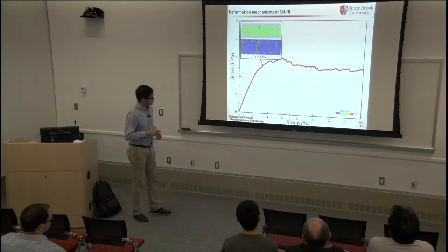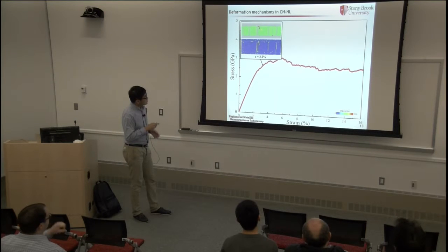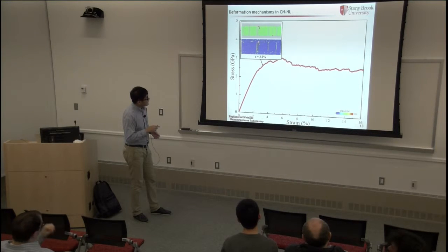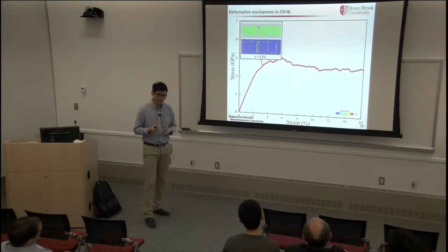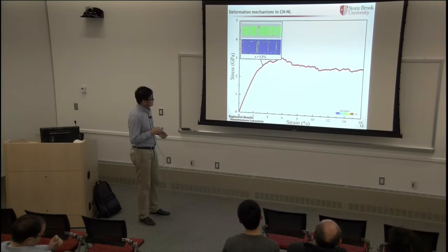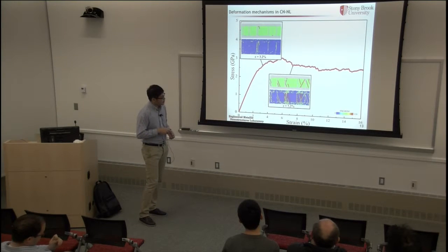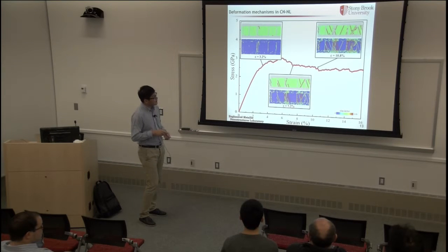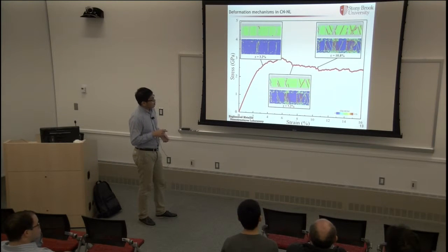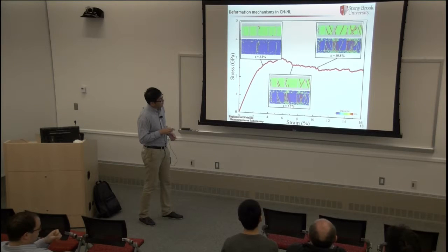First, let's look at the 3.2% strain. We see that there's a leading partial being emitted from the intersection of the grain boundary and amorphous-crystalline interface, where the atoms show a higher slip vector value, or a higher level of plastic deformation. And then this leading partial was followed by a trailing partial, and it leads to a full dislocation glide. And this full dislocation is absorbed by the lower amorphous-crystalline interface and triggers more shear transformation zones in this lower amorphous layer, which leads to another dislocation traveling upward. And also, in the neighboring grain, we see the deformation twin found in here.